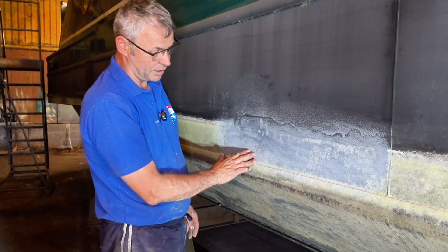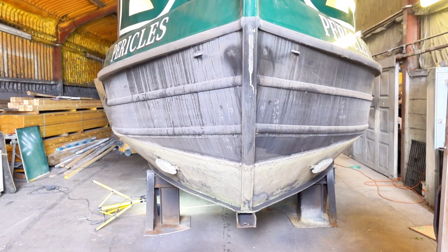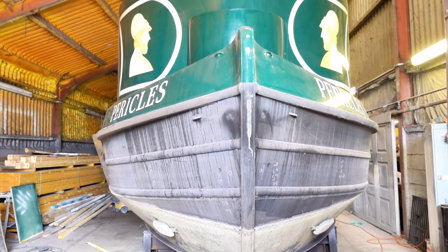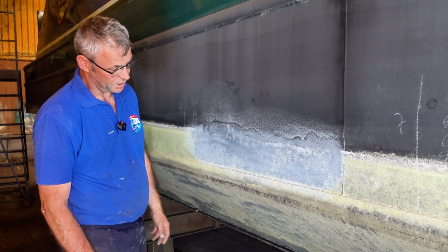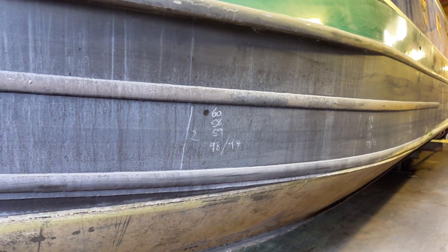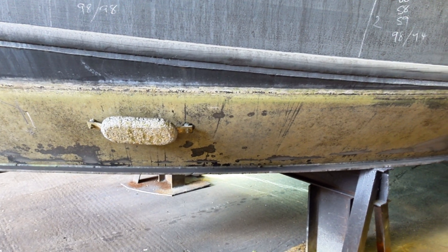When you're sanding it's really rock hard, and because of that shot blast profile it's literally stuck to that steel. By the time we've abraded it with probably a 180 grit, maybe even 120 to get rid of the algae, and then just smooth it off with a 180, we'll put another two to three coats of epoxy over it — which is going to give it another seven or eight years. And every time it comes back, that's all you need to do: sand it back and reapply more epoxy. You're just constantly building the layers of epoxy up, so corrosion never starts.